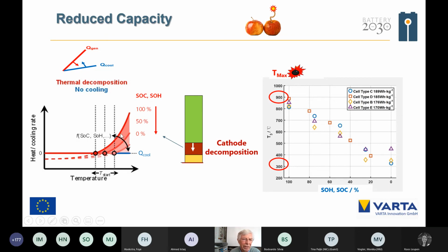If you have 100% state of health, you have a lot of cathode material which could be decomposed, and then the reaction is started. If you have a low state of health or a low state of charge, your heat generation is reduced. And you could see that here, that is the maximum determined runaway temperature. It depends on the state of charge and also on the state of health. If the cell is discharged, you could see the maximum temperature is 300 centigrade, and in full charge you have 900 centigrade.